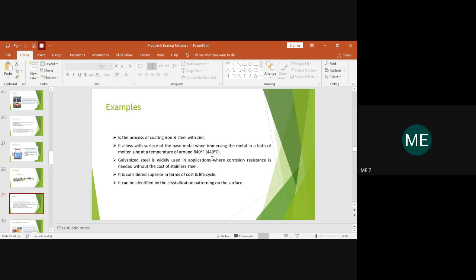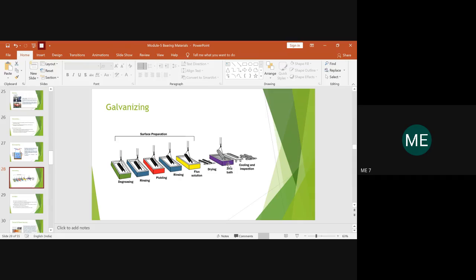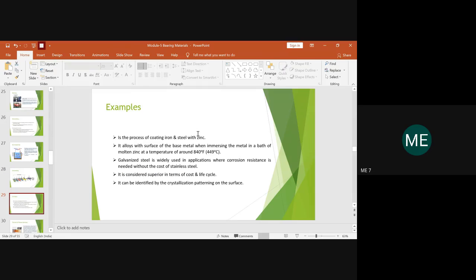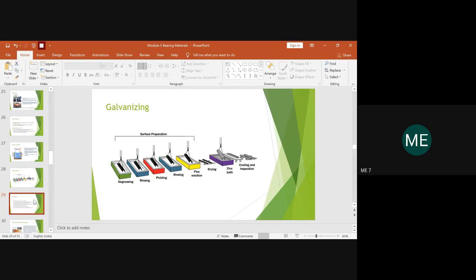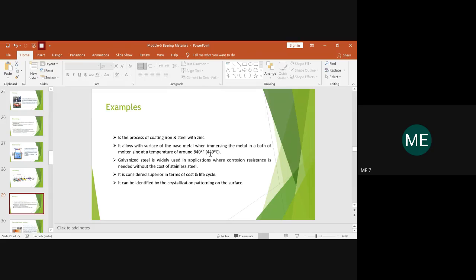Finally, the main thing I forgot to tell you is that you need to dip in the zinc bath for a particular dwell period of time, right? Related to that, take the example of coating an iron or steel rod with zinc. What happens exactly when you immerse it in the zinc bath? The molten zinc in this bath will be at a temperature of around 840 degrees Fahrenheit or 449 degrees Celsius. You will immerse the steel or iron rod in this molten zinc bath, which is set at 449 degrees Celsius.